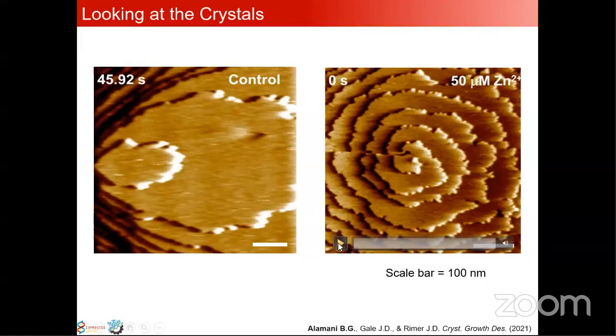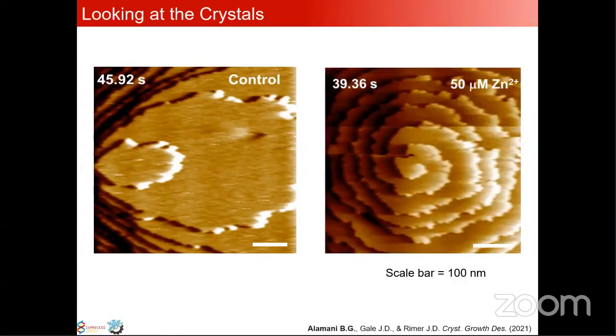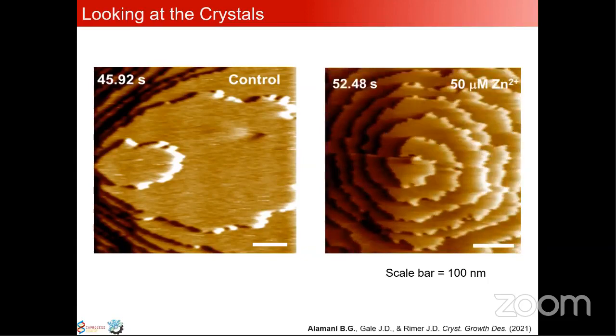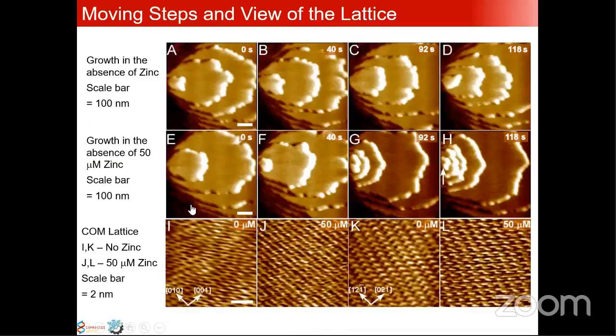Now I started to add zinc. What happens is that there was a change in the morphology. So you now have a circular shape. Both of these are still calcium oxalate crystal. It just so happened that the second movie shows you the morphology in the presence of zinc. So now we started to try to decipher everything, and we made snapshots of those events. Here is an illustration on the first row, from A to D. You see here the growth in the absence of zinc. So it's the usual one.